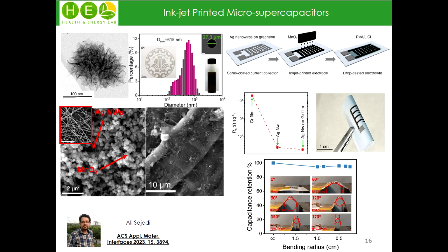For the current collector, we developed it based on graphene sheets prepared by liquid phase exfoliation. First, the surface of cellulose paper was modified with graphene sheets to have a more uniform surface, and then silver nanowires were loaded.